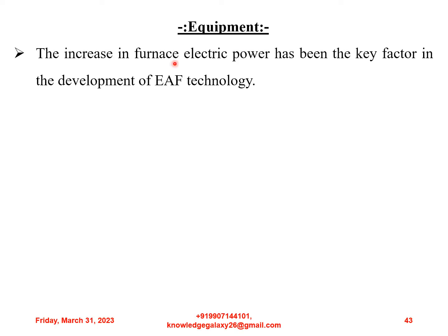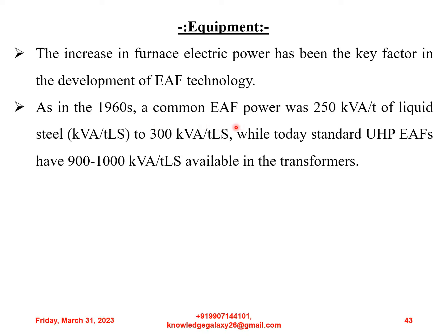Now let us describe and discuss the equipment used in electric arc furnace steel making. The increase in furnace electric power has been the key factor in the development of electric arc furnace technology. In the 1960s, a common EAF power was 250 kVA per ton of liquid steel to 300 kVA per ton of liquid steel, while today standard ultra-high power electric arc furnaces have 900 to 1000 kVA per ton of liquid steel available in the transformers.